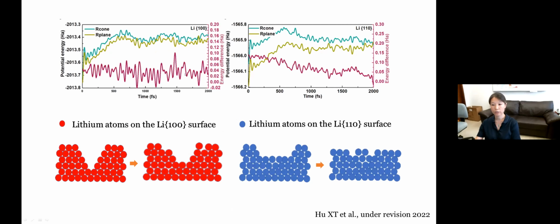We also compare the potential energy of the cone, which is the dark green, and the plane, which is the light green, for both the lithium 100 and 110 planes, right? And in both cases, we see that the potential energy associated with the plane is lower than that of the cone. But then at the end, when the pit of the surface is filled, in the case of the lithium 110, these two potential energies start to merge, right? Telling you they try to regain a flat surface. But then in the case of the lithium 100, there's not much change. Telling you the pit, once it forms, tends to remain there, right? So this is the message.